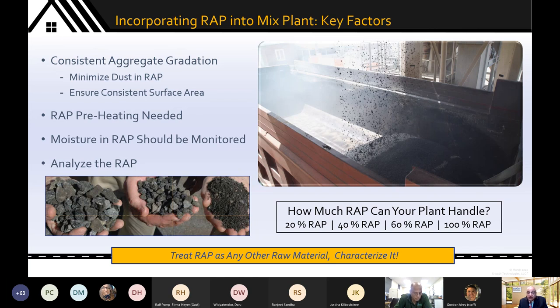Moisture content in the RAP is also very important. I tell folks all the time, put a tarp on your RAP piles. And the reason, again, is very simple. Moisture, and many of you probably have practical experience of this. In general, it is true that if your RAP is wet, let's say you were running 40% RAP all day long yesterday, there was some rain overnight, and your RAP is wet today, you may only be able to run 20 or 25% RAP today. Why is that? Well, because you've got to drive off the moisture. The moisture not only needs to be brought up to temperature, but you need to provide the latent heat of vaporization, which is a big chunk.